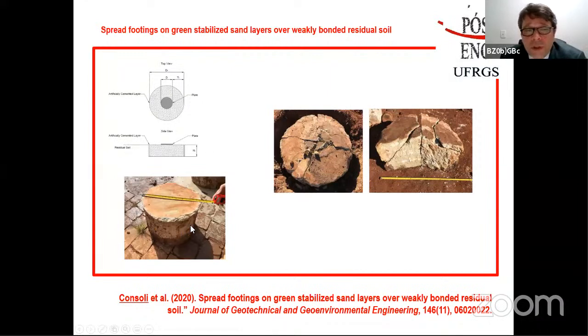Here is also another paper that was published in the Journal of Geotechnical and Geoenvironmental Engineering in 2020, in which we have improved in the field certain volumes, and we have put some steel plates on the top, and these would be some improved layers in order to increase the capacity of this plate load test on the top of it. And we see even the failures. What is interesting is that the cement that was used specifically was carbide lime together with ground glass. So two residues that were turned into cement, and we improved different areas and regions to check what was going to be the effective kind of failure mechanism that we would have in each one of these cases.